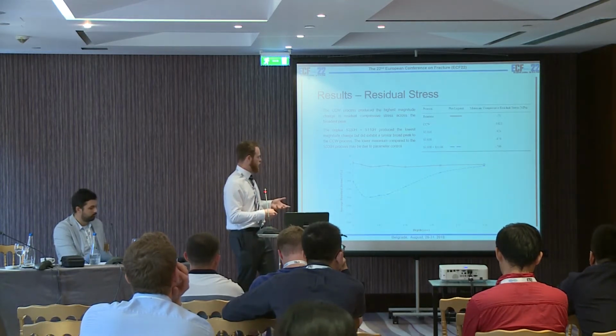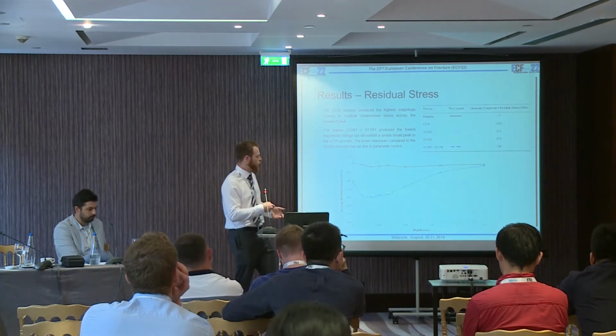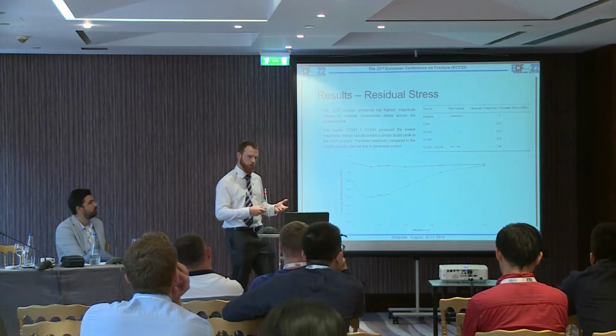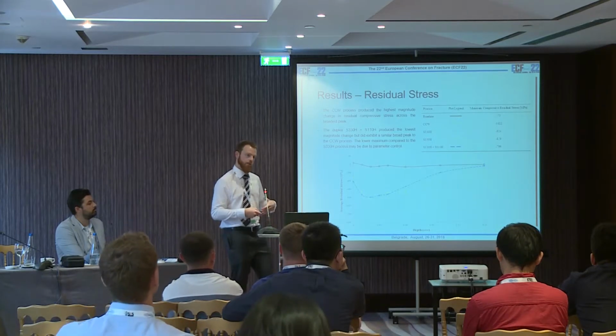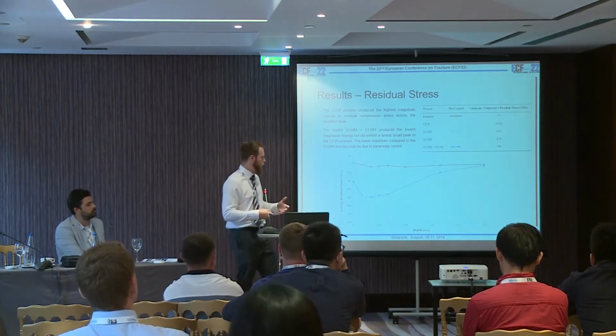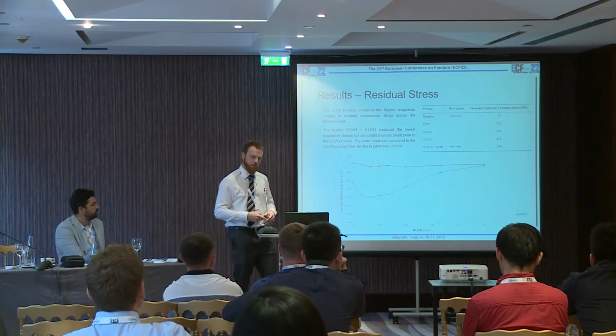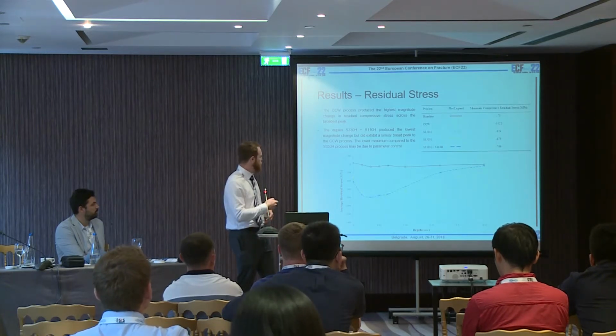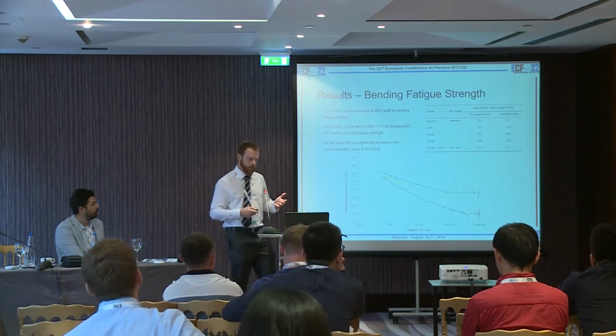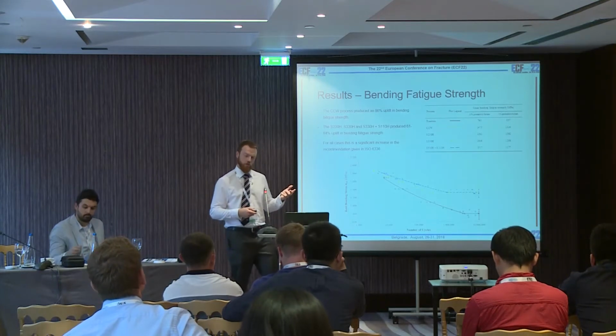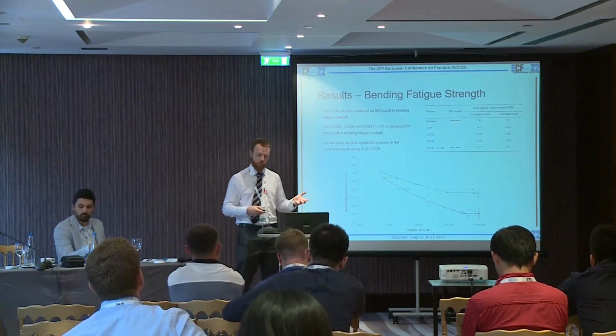So, for example, if we looked at the 230 shot size, within the shot that was used within that process, some of them will be 330 size and some of them will be 110 size. So I think that's a better reflection of that. And the results from the compressive residual stress are also reflected within the bending fatigue strength.